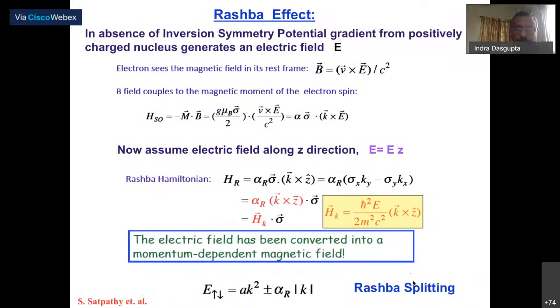Well, this is the spin orbit coupling that we'll be interested in in the present talk. As I was trying to tell, absence of inversion symmetry creates a potential gradient from a charged nucleus, which generates an electric field. Now this electric field, seen from the rest frame of an electron, manifests itself as a magnetic field. And this magnetic field couples with the spin of the electron. So you now have a K-dependent magnetic field. In a real system you can assume that this electric field, which appears because of broken inversion symmetry, is along the Z direction. Then you can substitute it here and recover what is known as the Rashba Hamiltonian, which has this specific form. I will talk about this Rashba Hamiltonian and the related Dresselhaus Hamiltonian as I move along.